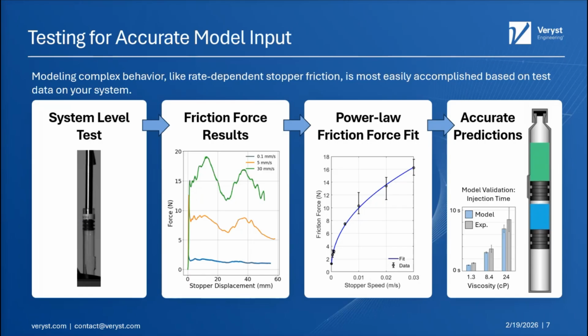So it turns out that predicting stopper friction from first principles is complicated, and there's a number of reasons for that. There are different physical mechanisms. It's usually a pretty small scale. The thickness of the lubricating layer is submicron. So for this particular project, rather than start from first principles, we instead experimentally measured the stopper friction at different speeds in our laboratory. We then fit an empirical power law curve to the average stopper friction, and then we were able to incorporate that into the mathematical model. And that gave very good predictions, but it also shortened the time to develop the model.